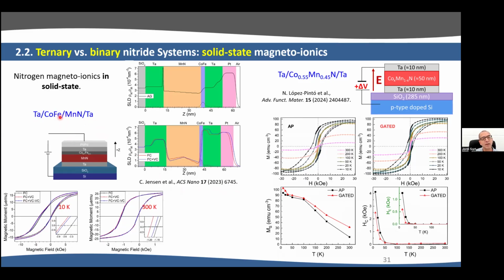First, what they did is a heating and field cooling process to induce an interaction between cobalt iron and manganese nitride. A typical fingerprint of this interaction is the shift of the hysteresis loop, which is called exchange bias. And this phenomenon is actually very much used in spin valves and sensors nowadays in computers. And there is exchange bias both at 10 Kelvin, but also at room temperature.